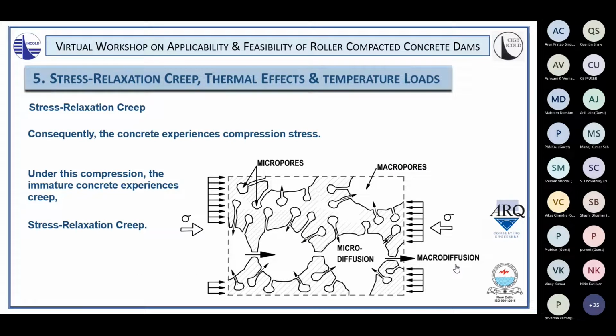Under this compression stress, the immature concrete experiences creep through which that compression stress is relieved or relaxed, and hence the name for this type of creep: stress relaxation creep. And one credible theory that has been advanced to understand what is happening in this process considers the fact that the immature concrete under compression experiences a situation where moisture is squeezed from the micropores in the paste into the macropores.